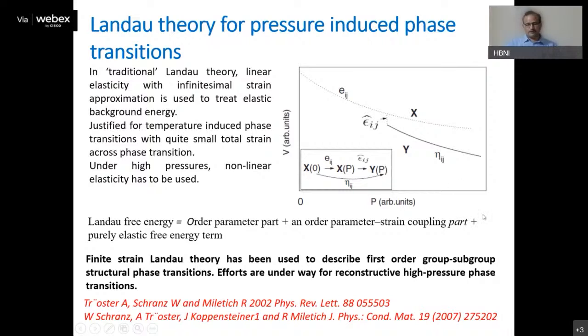In case of pressure-induced phase transition, if you see the volume versus pressure plot, in the initial phase the volume decreases, and this decrease is nonlinear as we discussed in the equation of state, because as you go to higher and higher pressures, the compressibility reduces. So your bulk modulus increases, and that's why there is lower change in volume as you go to higher pressure. At some pressure, there is a phase transition.